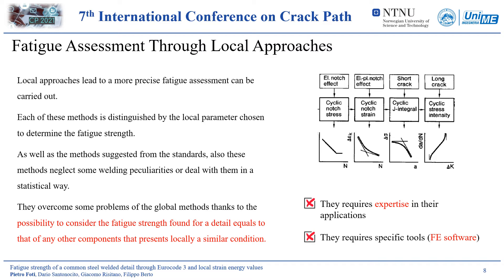A more precise evaluation of the fatigue life of a component can be performed through the so-called local approaches, although they also neglect, like the global approaches, some welding peculiarities or deal with them in a statistical way. This is due to the fact that it is not possible to take into account every aspect that affects the fatigue life of a component — it would require a very high computational effort, leading probably to no appreciable differences in the assessed fatigue life. Each of these methods considers a local parameter whose critical value has the important advantage of being independent on the global geometry of the component considered. Anyway, the local approaches also have some limitations: first of all, they require certain expertise, considering that each method has its own theory and procedure to be applied. Second, they usually require the use of finite element software, with, for some approaches, a significant computational time due to the refined meshes required.